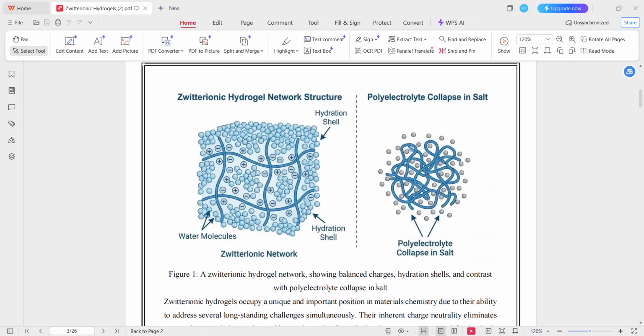Now, this figure shows a Zwitterionic hydrogel network. You can see polymer chains containing both positive and negative charges. Around these charge groups, there are multiple layers of tightly bound water molecules, forming what we call a hydration shell. This figure also contrasts Zwitterionic hydrogels with traditional polyelectrolyte gels. In polyelectrolyte hydrogels, when salt is added, the polymer chains collapse due to charge screening because the electrostatic forces of repulsion reduce. However, in zwitterionic hydrogels, the opposite happens. When salt is added, internal electrostatic attractions are screened, allowing the polymer chains to expand. This phenomenon is known as the anti-polyelectrolyte effect, and it is a defining feature of zwitterionic hydrogels.